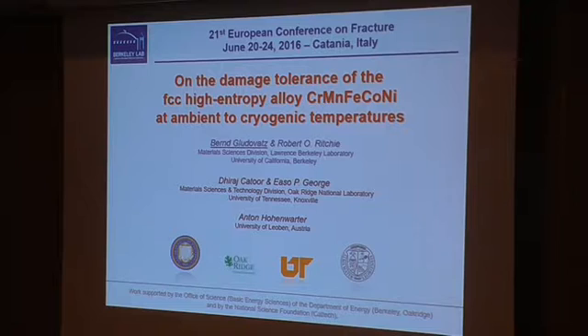So now that Easo had this material lying around, he got curious about the properties of this alloy, so he processed it to different microstructures between 5 and 150 microns. As we can see, after processing, from our SEM, EBSD, and TEM images, we had homogeneous equiaxed grain structures in all cases. There were a large number of annealing twins after recrystallization. From the EBSD scans, we can clearly see that this was only weakly, if at all, textured. And of course, it was a single-phase microstructure, and the grains were, after recrystallizing, basically dislocation-free.